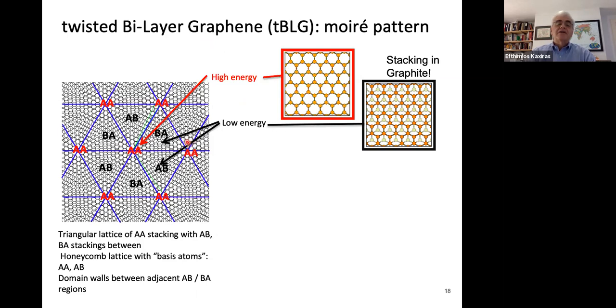And there are other regions where the top layer, here it's shown again, hides only half of the atoms of the bottom layer. So you see the other half of the bottom layer atoms. And these are referred to as AB or BA stackings. They're equivalent by symmetry. And in between these regions, you get these domain walls. So you get these three important features: AA stackings, which happen to be high energy stackings, AB or BA stackings, which are the low energy stackings, and finally the domain walls between those regions.